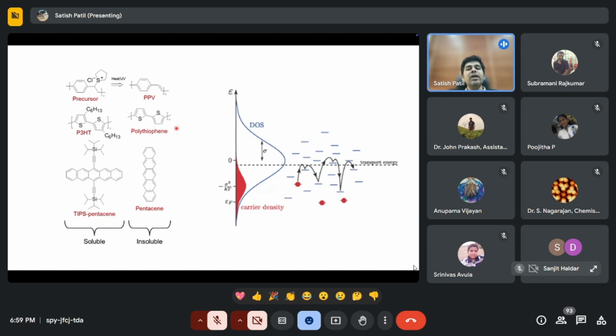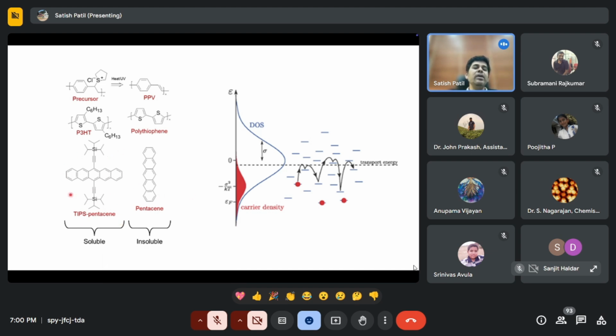Whereas in this kind of polythiophene, you don't get a very high molecular weight because the polymer precipitates out before it grows any further. So without solubility of a polymer in a common organic solvent, you don't really build a very high molecular weight material. So that limits the property of a polythiophene. Similarly with pentacene. Pentacene is a very unstable material, and you introduce this TIPS group here. This becomes TIPS pentacene. In small molecules, you increase the solubility, and then you can really make devices out of it from solution.